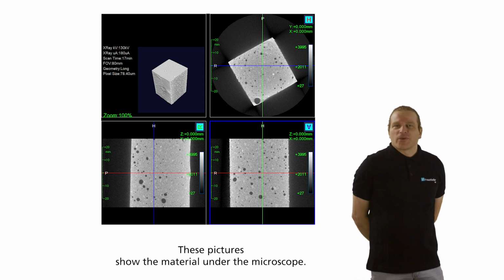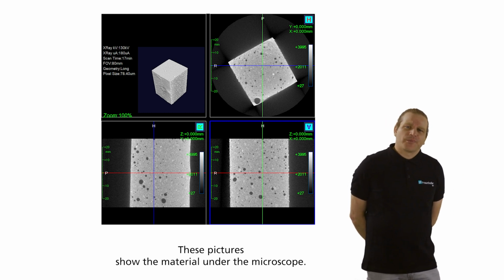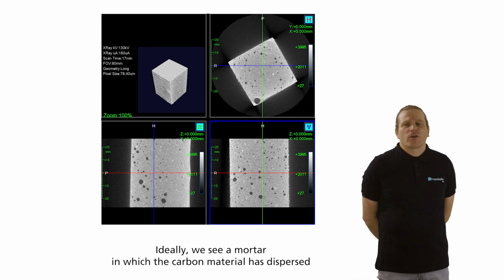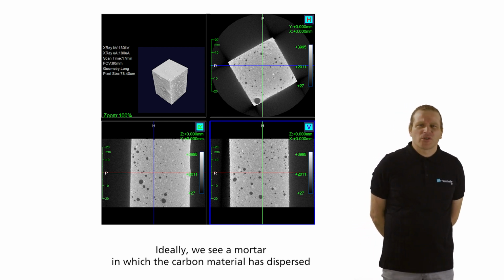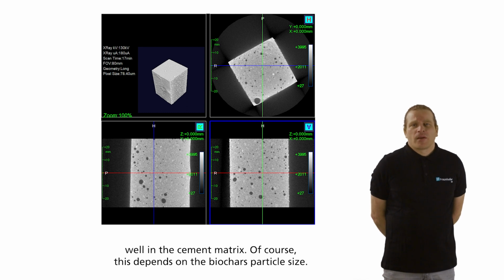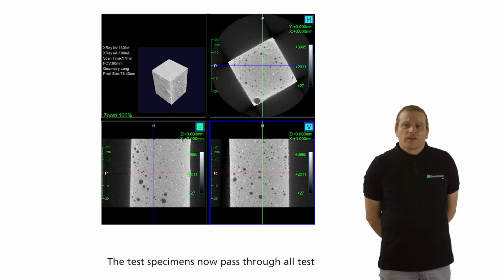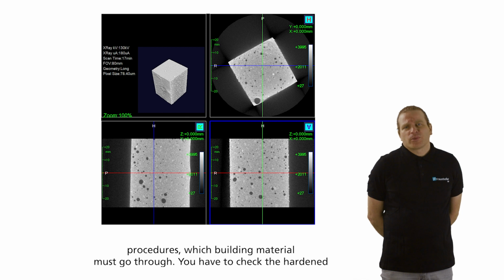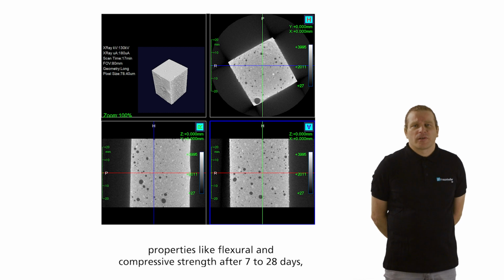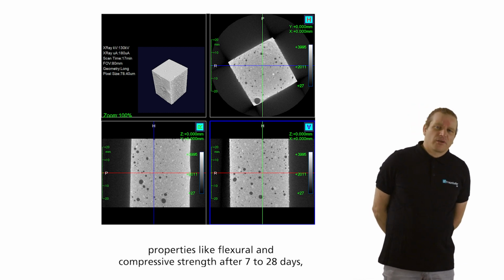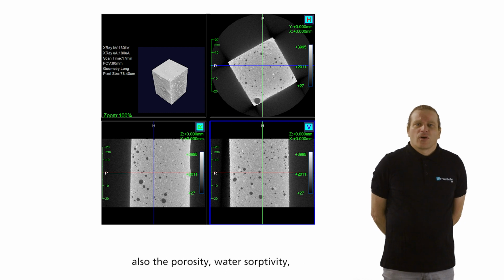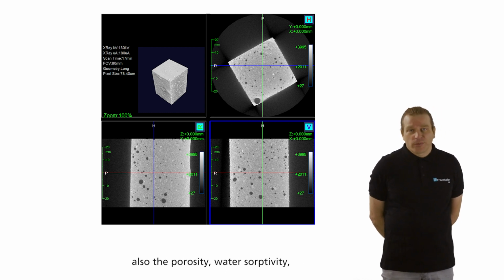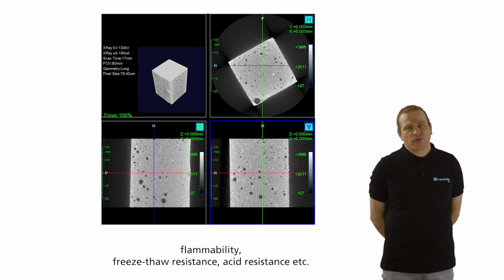These pictures show the material under the microscope. Ideally, we see a mortar in which the carbon material has dispersed well in the cement matrix. Of course, this depends on the biochar particle size. The test specimen now passes through all test procedures which a building material must go through. You have to check the hardened properties like flexural and compressive strength after 7 and 28 days, residual porosity, water sorptivity, flammability, freeze-thaw resistance, acid resistance, and so on.